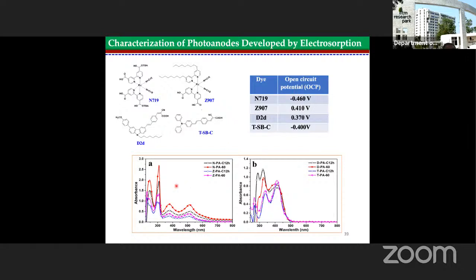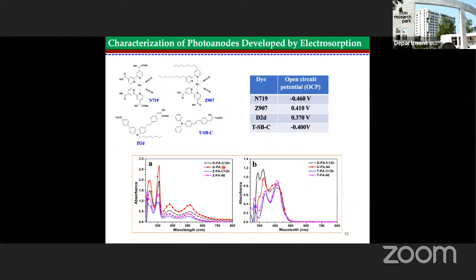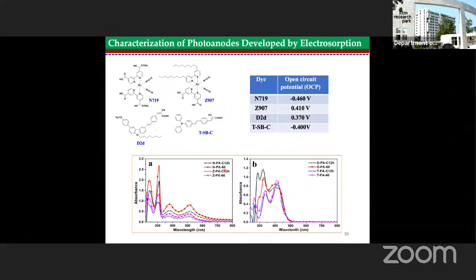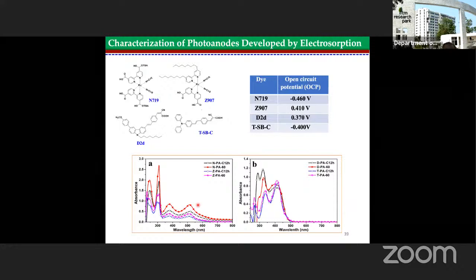So you can see this is the absorption spectra with wavelength. This C represents the conventional dyeing process. Whenever you don't have a C, it is called an electroabsorption process. N represents N719 and Z represents Z907 dye. As you can see, whenever we do electroabsorption, the absorption is higher. That means more dye gets onto the surface, therefore more light harvesting can happen.